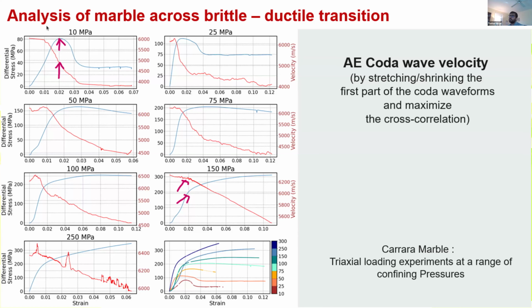So if you look at the experiment on the top, we have strain on the x-axis, and you're deforming the sample. Once you go to yielding, then the differential stress is going to keep decreasing. There's a change in the velocity. It starts off a little bit before you have the peak stress. That's probably indicating some form of changes in the damage occurring. And then we see the primary change in the velocity during the yielding phase. And subsequently, during the more plastic deformation, there's not a very strong change in the velocity. But you can still see the different regions of the deformation behavior and the rheological response in the velocity. And we can do the same for all the different experiments.